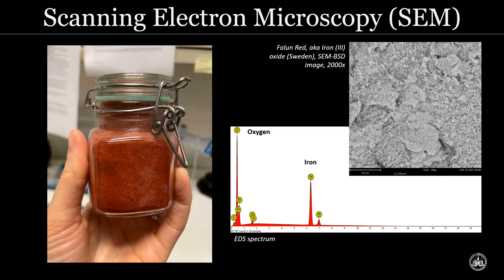To get confident identifications for certain pigments, I can analyze them with our scanning electron microscope, or SEM. Our SEM can achieve very high magnifications, above 100,000 times, although I never really have to go that high for pigments. And it's coupled with an energy dispersive spectrometer, or EDS, which gives me elemental data at any point that I target in the sample.